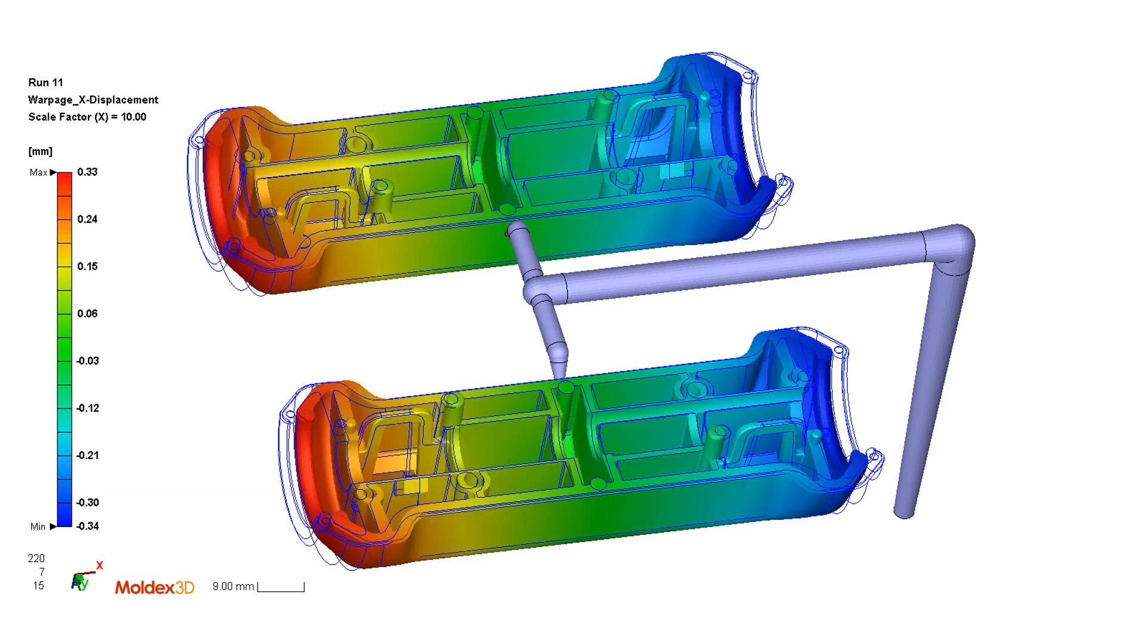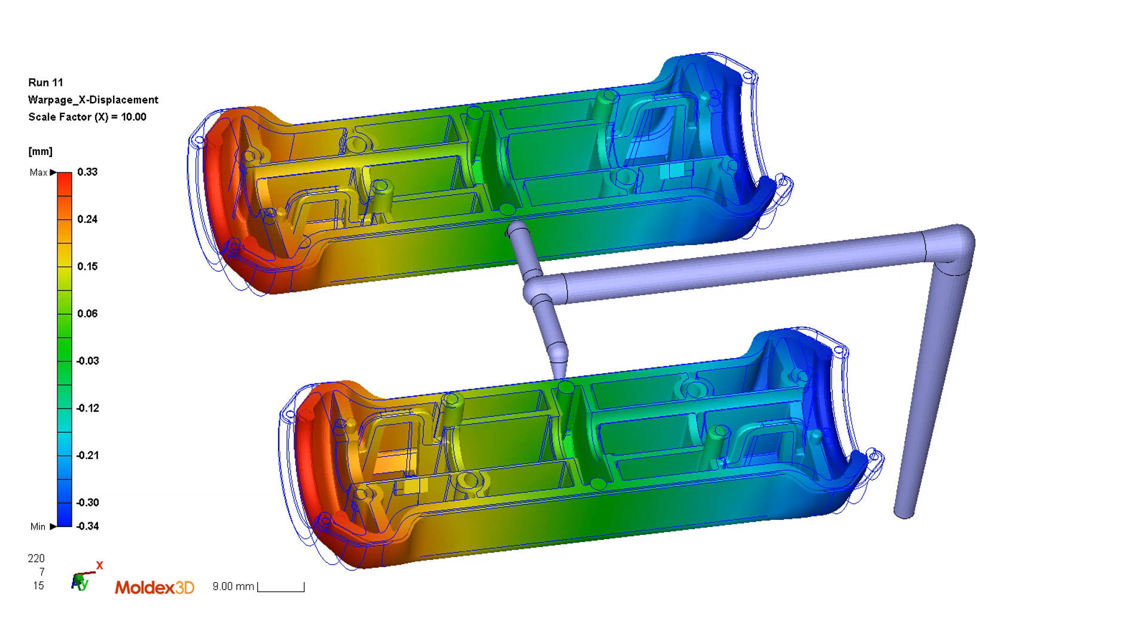Here you go this is the X direction. The red area is moving towards the center location of the gate by about 0.33 millimeters the blue is also moving towards the center of the gate by about 0.34 millimeters. So the entire part is shrinking in the X direction by about 0.67 millimeter. That includes the natural material shrinkage.